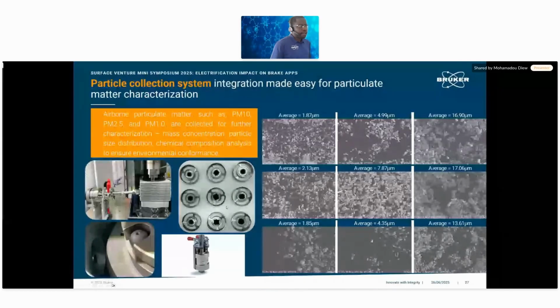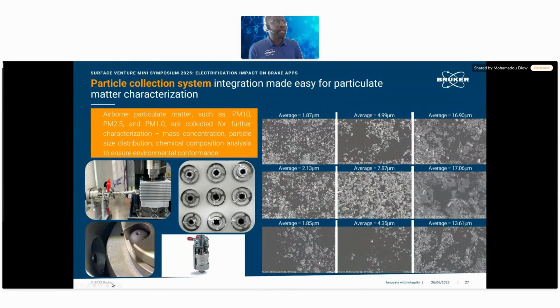Adding a particle collection system, as I said at the start, we add a chamber tubing with the impactor here. We can collect particles within different types of filters: 1 micron, 5 micron, and more than 10 micron. And we have the possibility to characterize each of them for 3 different types of testing. For example, we can run a certain number of tests and compare these different sizes of particles. And using the SEM, we can also try to get the distribution with a statistical approach, or do chemical analysis on it to get the chemistry of each of these materials.